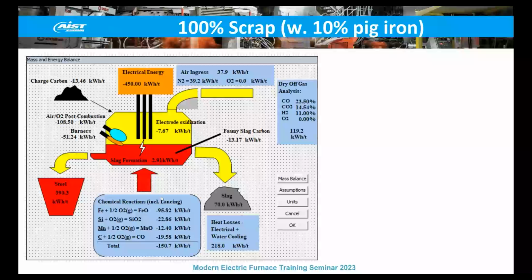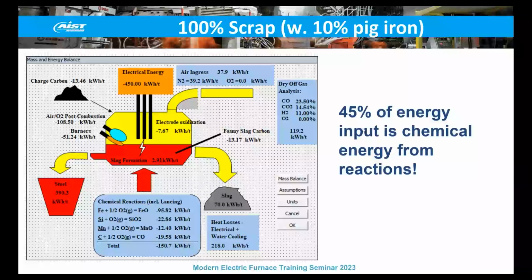So this is looking at a first mass balance—a no-DRI, 100% scrap charge with, say, a 10% merchant pig iron. He's just trying to show a mass balance here, where all of your energy is going, what types of energy there are. In this scenario, 45% of the energy is chemical, so you're getting energy from the pig iron and from the carbons, the coals that you're adding to the furnace. The electrical input here is 450 kilowatt hours per ton.